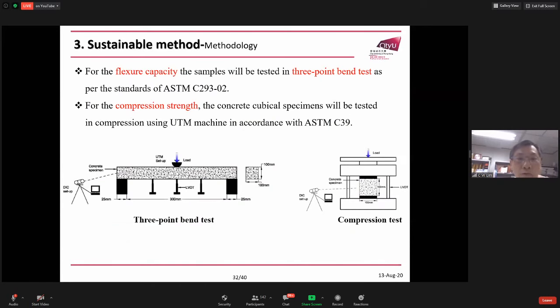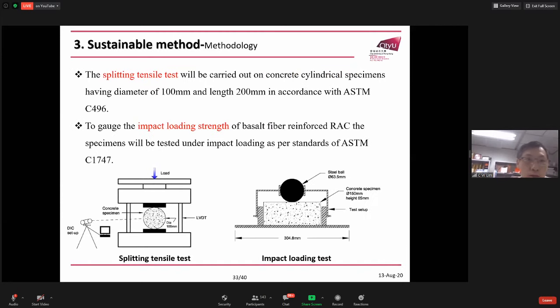And after that, we wish to do some tests to show that the result can actually be obtained and the objective can be achieved. First, we wish to do two types of tests. One is the flexural capacity test, for which the standard ASTM standard will be followed. And the second one is the compression test, which we also follow the ASTM standard. Next, we will also do the split tensile test and also the impact loading test for the strength of the basalt fiber reinforced RAC.